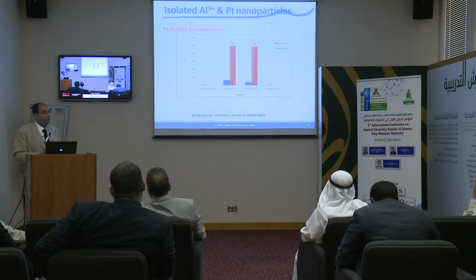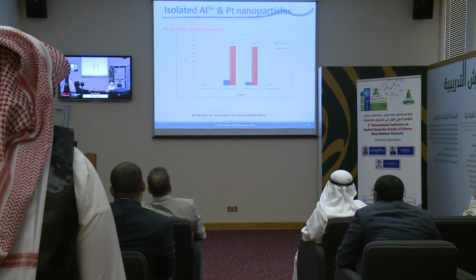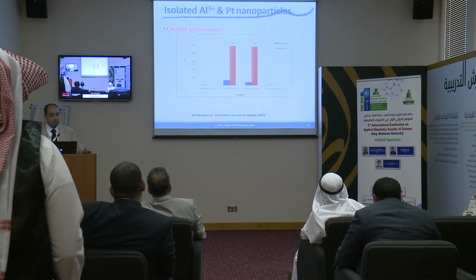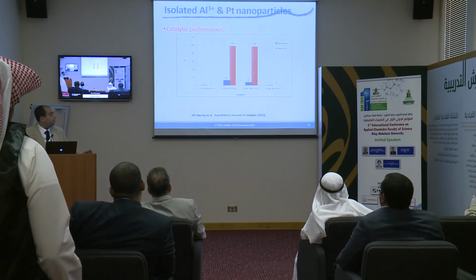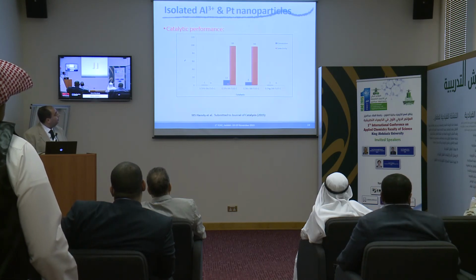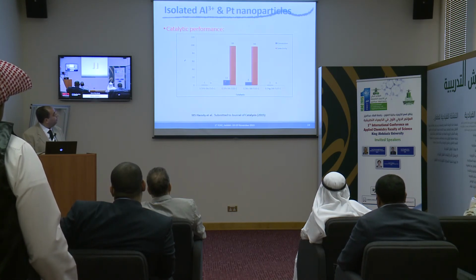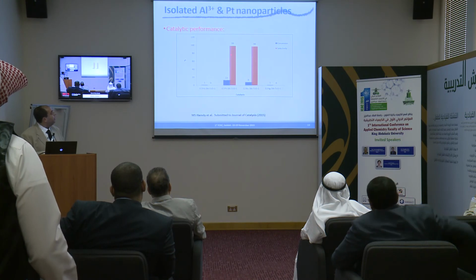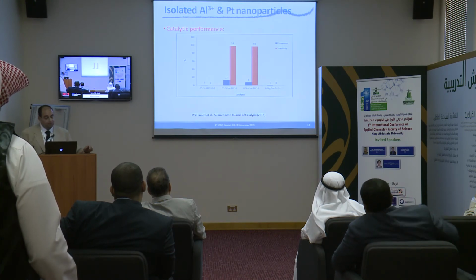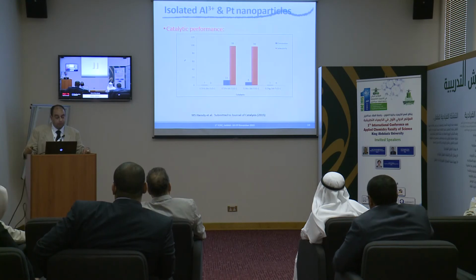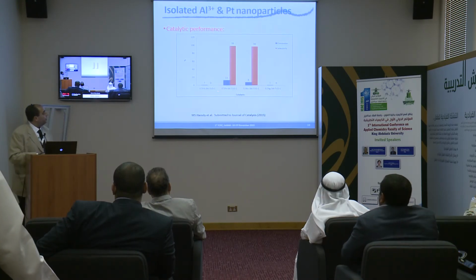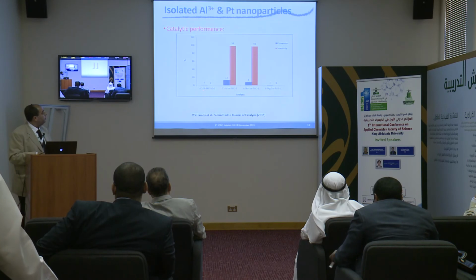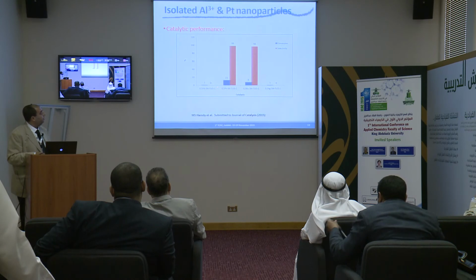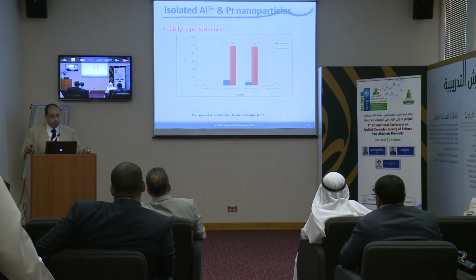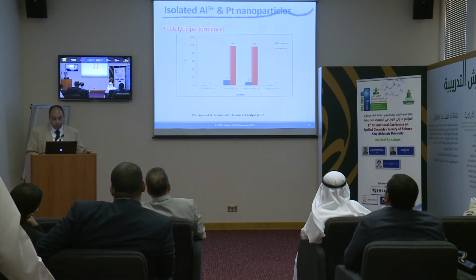And this is the catalytic activity that we get, and actually this is the first time that this reaction has been performed in liquid phase reaction. By using platinum aluminum TUD1, you will get 13% conversion and 99% selectivity towards 2-methyl propanol, the desired product. We replaced platinum with ruthenium, with silver, with palladium. Ruthenium gives also considerable activity, but not as much as platinum, and this work has been submitted recently to Journal of Catalysis.